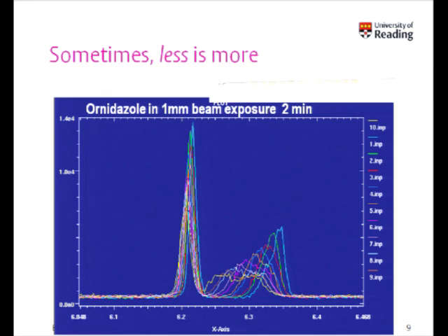The other thing I would just say briefly about synchrotrons, and in particular the third generation with the insertion device, is that sometimes actually less is more. We find particularly with organic materials, the destructive power of the incoming beam can be quite severe, and this is one of the first ones that we saw a really, really severe effect on. It's actually an antifungal drug called ornidazole, and what we have here is a 1 millimeter capillary exposed for 2 minutes on ID31 at the ESRF, Andy Fitch's beamline.